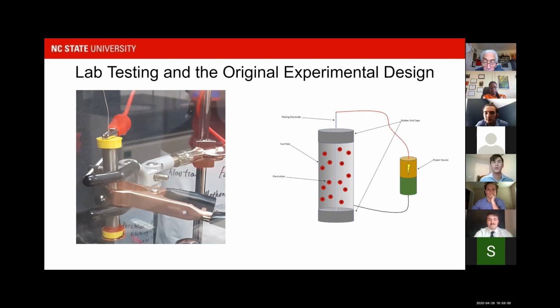Ideally, it's a chromic acid solution. It fills the inside of the tube with end caps that have been 3D printed, with the central anode fed through the center of the tube, to provide an even coating and even electric field so that the ions can plate evenly across the entire inside diameter. For our anode, we decided to use titanium because we found a patent from multiple years ago that described using a titanium anode, so we decided that would probably be the most feasible option. Then we conducted tests to determine the feasibility of it.